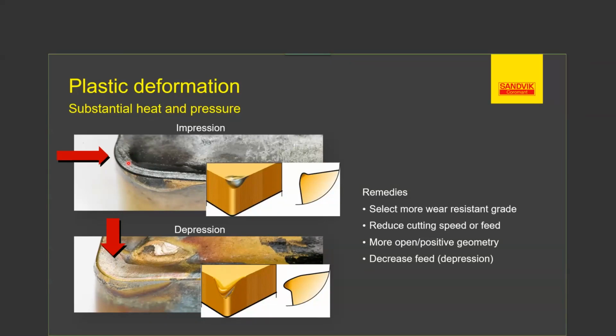The other thing is sometimes you get these types of wear mechanisms, but we don't stop the insert early enough. So essentially what happens is you'll get a whole edge line break. And what you think might be happening is, oh, I'm just losing my edge because it's not tough enough, and then you'll change it to a tougher insert. The fact is you should actually go to a more wear resistant or harder insert to compensate for this plastic deformation. So what we want to do is make sure we're stopping our inserts before they get to the final failure, so you can read the wear properly and make the proper adjustments.